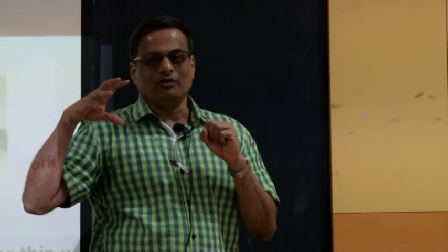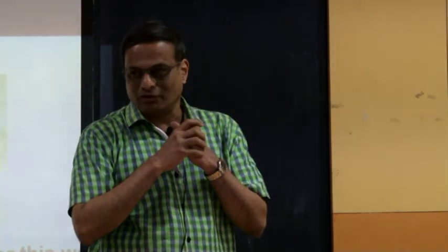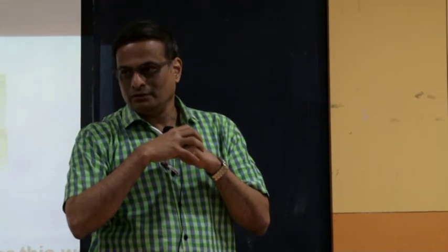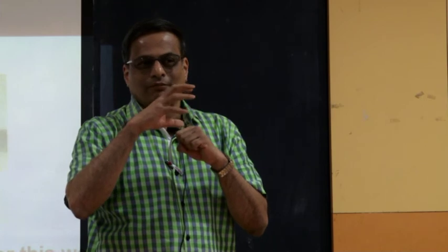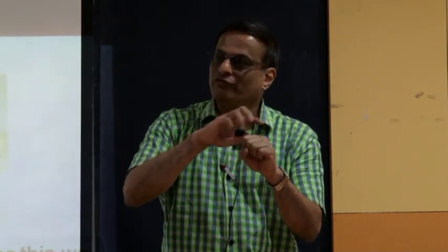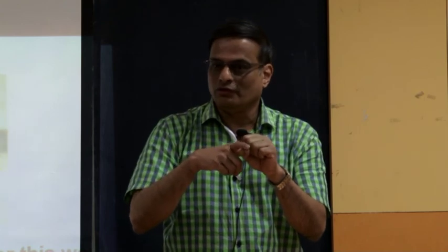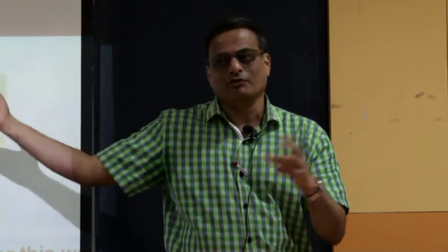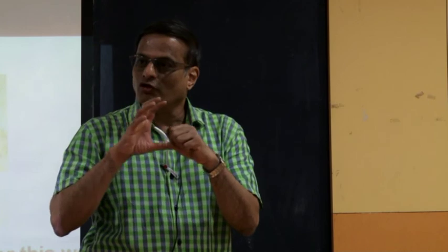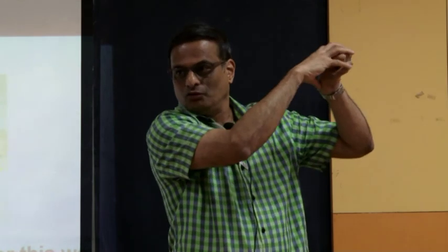What happens is not all shells will stick to every core. The shell may not even adhere to the core. There may be a maximum thickness of the shell for every core. So although I show a schematic, and it looks very nice, I can draw any circle I want. But in real life, you cannot put any ratio of shell to core that you want to. So this is one within the other, core shell.